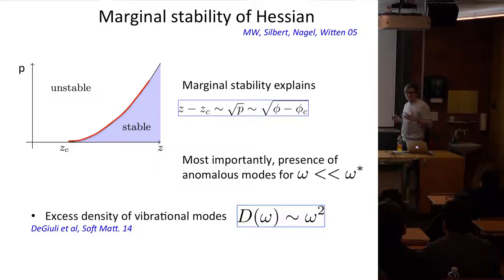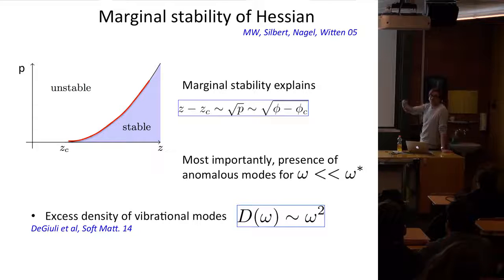But most importantly, if you look at vibrational modes below this omega star, what you find in those packings is that even at frequencies much larger than when you reach the plateau, you have many more modes than what you would expect. And that can only happen if you're very close to this line. What you can prove too is that if you're right on this line, you would have plane waves, but in addition to that, you would have other modes, and they would contribute to the density of vibrational modes in a quadratic way. So in 2D, it's just like the Debye, but in 3D, for example, it's larger. That's independent of the spatial dimension.